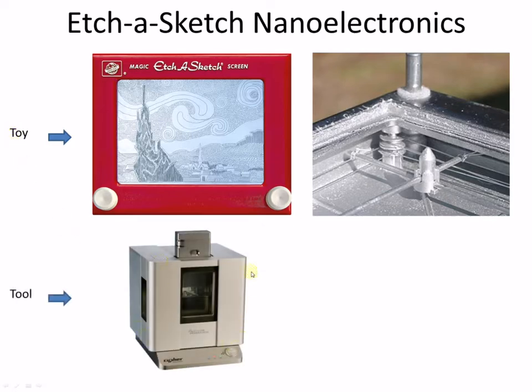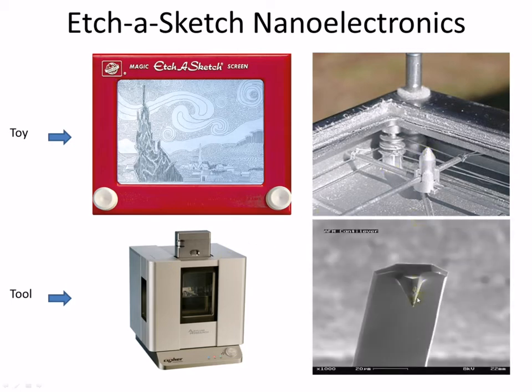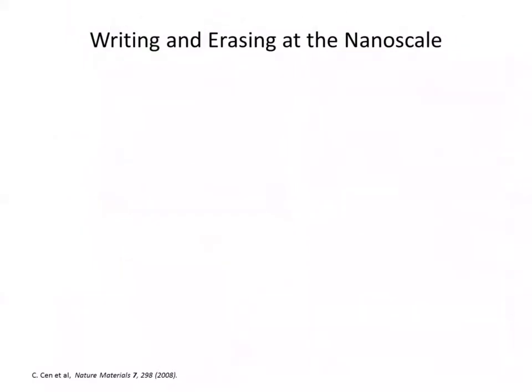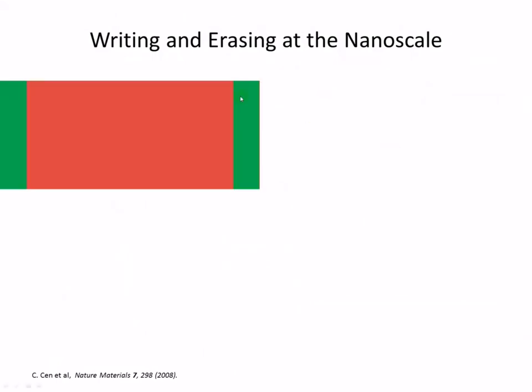So we use atomic force microscopes, and instead of a blunt stylus like this, we use a very sharp AFM probe, which has been coated with metal and can allow us to apply voltages to the top surface of this oxide heterostructure. So the way that it works is as follows. The green areas indicate regions that are conducting, or the electrodes. And so we can monitor the conductance by putting a voltage, let's say, on one end and measuring the current on the other end. And in this region here, we have an insulating area, and so there's no way for electrons to flow from one side to the other.